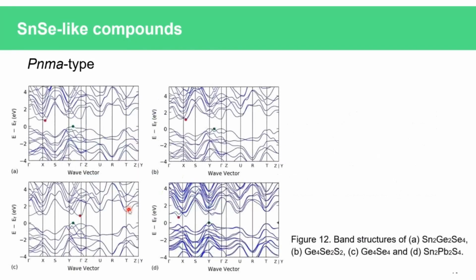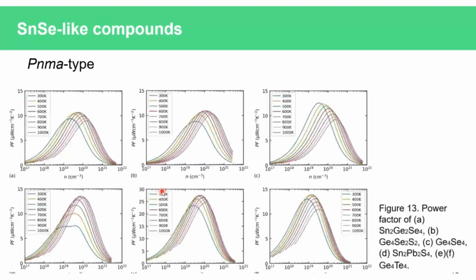This page shows their band structures. They are indirect gap semiconductors, and there are multiple band valleys near the gap for both conduction band and valence band. Meanwhile, these band valleys are highly anisotropic. Since these compounds belong to the orthorhombic crystal system, the band degeneracy of these band valleys is not very high, usually equal to 2.